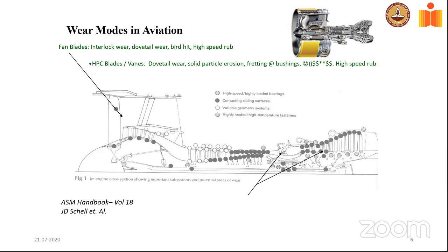And what you would also see is that the engine is rotating. It's on the wing. It's taking off from the runway. You can have sand and snow and salt during winter, and it could pick up all the sand into the engine, which would cause erosion. You could have flights going back and forth between Bombay and the Middle East, for example. Bombay is dry and dusty for 8 months in a year. It's very wet for 4 months in a year, but it goes into the Middle East, and what it picks up again is sand, and you have solid particle erosion taking place, which is very severe. So you have solid particle erosion, you have high-speed rub, you have fretting, and you have lubricated sliding with bearings. That's aircraft engines for you.